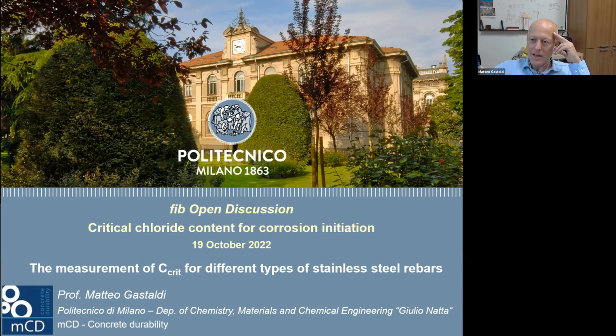For the second question, if you apply a current in order to move chloride, you have also the problem related to the current applied to move chloride. So I consider this a possible solution, and I agree with you that this is another possible solution. We moved from a solution in which we do not have the problem related to the circulation of a current, so we decided to mix in chloride, in order to have the chloride at the steel surface in a controlled way and in a very fast way, because we mix the chloride, so we have the chloride at the steel surface. And we measure this also at the end of the test in order to be sure that we have not a change in the amount of chloride at the steel surface. This is the logic.